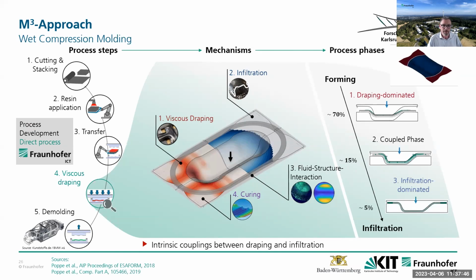First part is dominated by drape mechanism, membrane, bending, contact, compaction. Then towards the end of the forming process, the relevant fluid pressure occurs locally. This is critical for fluid structure interaction, so we can have a fiber displacement by having this resin being squeezed out. And the last 5% approximately are characterized by compaction and high fluid pressure. Forming is largely completed at that point.